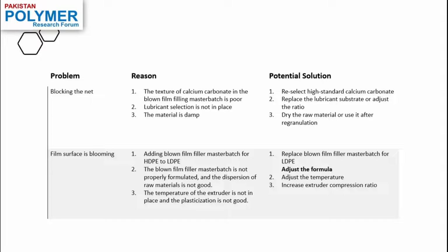So if the calcium carbonate you're using doesn't have a proper uniform texture, or you're not using the right quantity or the right type of lubricant, or if your material is humid or damp, all these reasons can cause blocking of the net or the sieves in the extrusion process. So this is a problem that can occur even during the processing stages, and the potential solution to this problem can be selecting a very high standard calcium carbonate, a calcium carbonate that has a uniform texture.